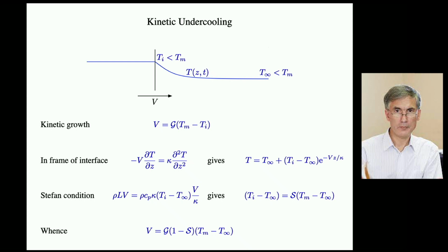The effective Stefan number is the actual Stefan number times the solid volume fraction at the interface. What was happening in there was a lot of little crystals growing up like this, albeit with a smooth envelope. The solid fraction is not very high, so there's not much latent heat release at that interface. So that effective Stefan number is low.